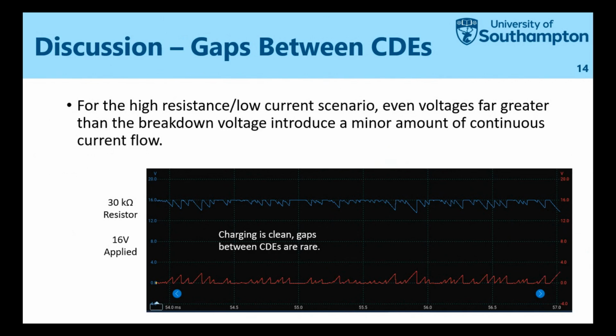But you can see that the charging is still clean. There are some gaps, but they're not quite as dramatic as when I had the 12 or the 150 ohm resistor. This waveform here, I've cut out only 3 milliseconds, but it's easy to count the amount of discharges. It's easy to park that in MATLAB and say count the amount of peaks, please, and it'll give you a clean one.